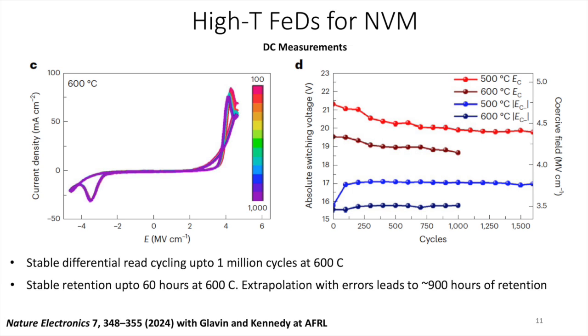This is very promising, right? I mean, 900 hours. So if you are worried about losing the data, you will have to worry about refreshing the data once every 900 hours. That's perfectly reasonable. That's perfectly acceptable. Right? So the other thing to keep in mind, and going to slide 20, is that you can also read and write the data many, many times. This is a much harder thing to achieve because every time you try to read and write data, you damage or cause defects within the material in any type of memory material. And so write endurance is typically hard to achieve.